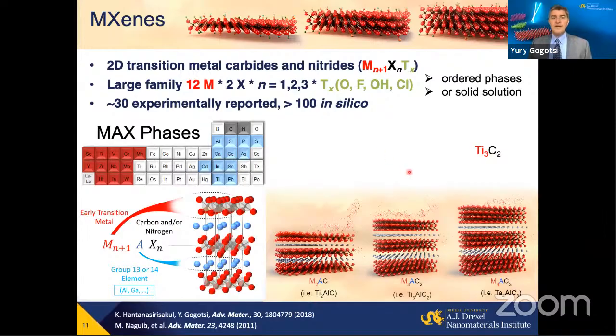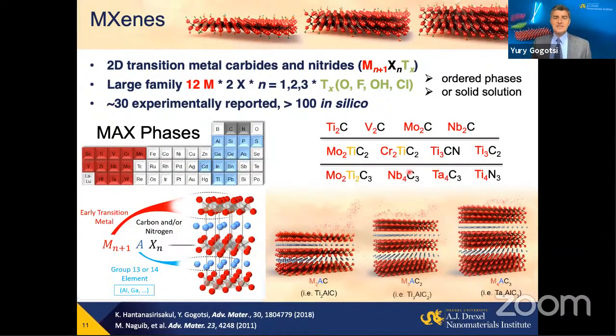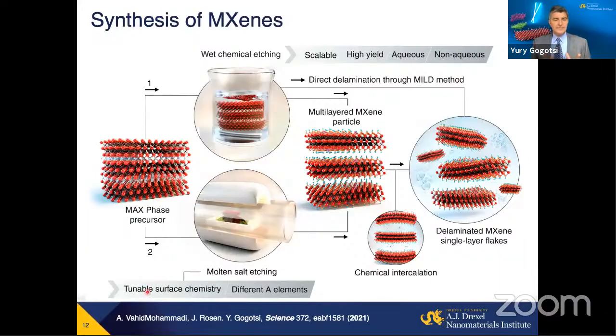One of the goals is to also make MXenes from elements so that we won't depend on the availability of precursors, which actually limits the number of MXenes we can make today, as we need to make the precursors first. But what is also important to mention here, when you do synthesis of MXenes, you cannot just take this layer structure and easily exfoliate it, as is done in the case of, say, graphite or molybdenum disulfide or vermiculite clay. There are strong metallic or covalent bonds between the A element or carbide layer in the structure of the layered precursor and the carbide or nitride layers, which would form MXene. So we have to selectively etch it.